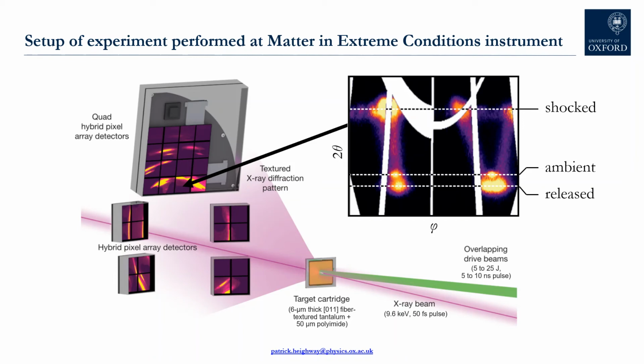Now, since the released material is, by definition, no longer subjected to stress, that expansion has to be interpreted as thermal expansion. That is, the crystal has overall expanded because it is hot. Thus, if we know the thermal expansion coefficient of tantalum, we can convert the increase in volume measured directly from the diffraction into a release temperature.